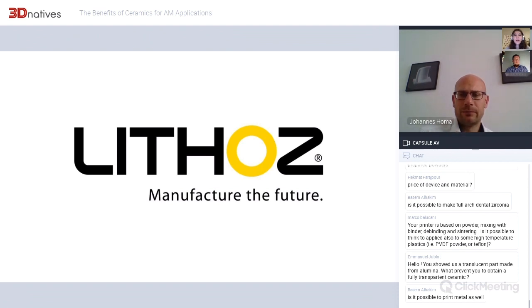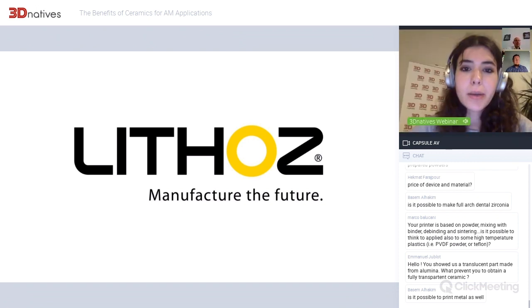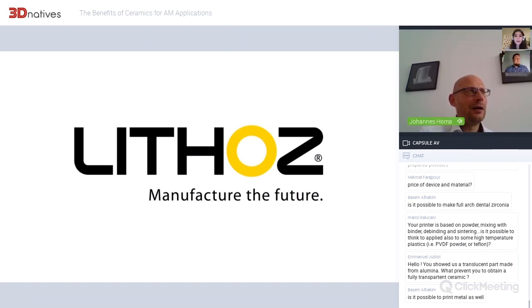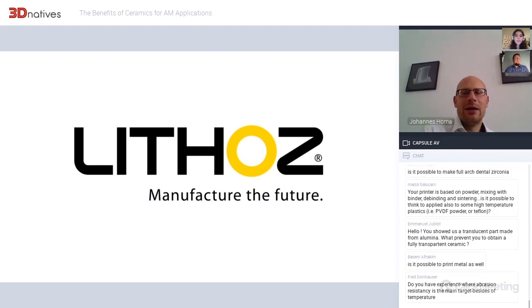And actually, what's the minimal grain size in alumina, if someone asks? The minimal grain size to get it transparent, you mean? The grains we usually have are around 100 nanometers as the starting grain size. But basically we can use all grain sizes, from a couple of tens of nanometers up to hundreds of micrometers. That's a really broad range, but of course you need a dedicated powder to be able to get a translucent or transparent ceramic.